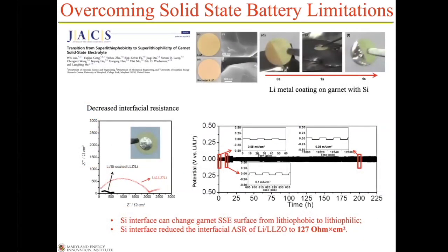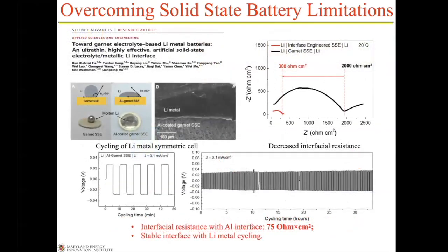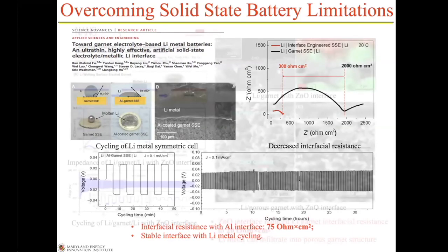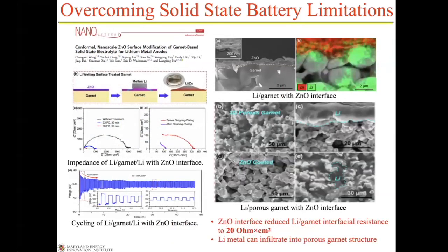We've done this by a number of different materials, I should say, all with the same effect. Here you're seeing the effect of using an additional layer. This is just a coated one of silicon. This is another one, aluminum. Again, the same thing. It wets, it reduces the interfacial impedance and allows the cell to cycle at high current densities without any degradation. This is zinc oxide. Now we're starting to see a structured interface, and I'll come back to this again.